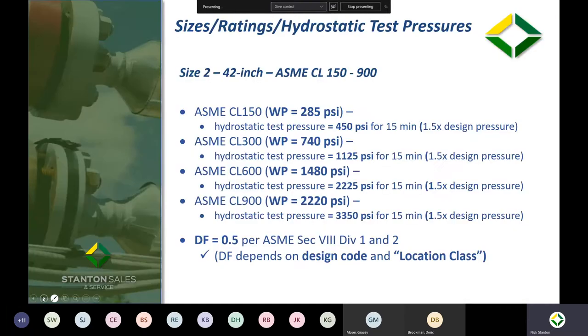Here's our rating, size 2 through 42 inch, class 150 through 900 insulated joints. So for example, the class 150 insulated joint has a working pressure of 285 PSI. So we follow the B16.5 ratings. There's class 600, working pressure good to 1480. So again, it's tested to 2220 PSI for 15 minutes. Had an order last week from Consumers Energy that called for an 8-hour hydro test. That's fine. Design factor 0.5 typically, ASME Section 8.